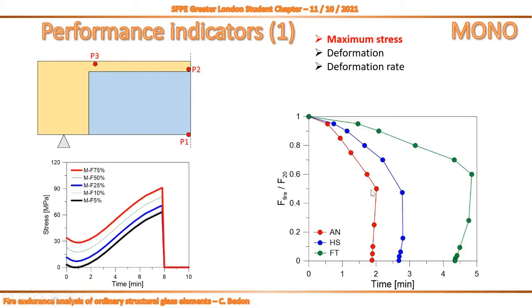You can see also what happens in the chart on the right, what happens if we keep track of, let's say, the loading condition leading to stress fracture in glass when we use different glass types: annealed, heat strengthened, and fully tempered. You will see that there is no proportionality of our resisting domain. So we are talking about the limit condition in which we can sustain both the mechanical and thermal loads compared to the actual mechanical resistance of glass. There is no more proportionality.